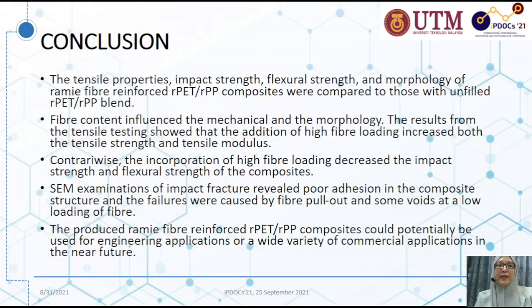For conclusion, the tensile properties, impact strength, flexural strength, and morphology of the ramie fibre reinforced recycled PET, recycled PP composite were compared to those of the unfilled recycled PET, recycled PP blend. Fiber content influenced the mechanical properties and the morphology. The result from the tensile testing showed that the addition of high fiber loading increased both the tensile strength and tensile modulus. Contrariwise, the incorporation of high fiber loading decreased the impact strength and flexure strength of the composites.